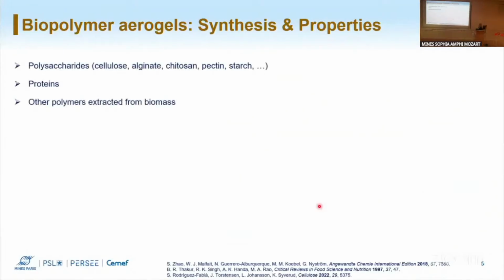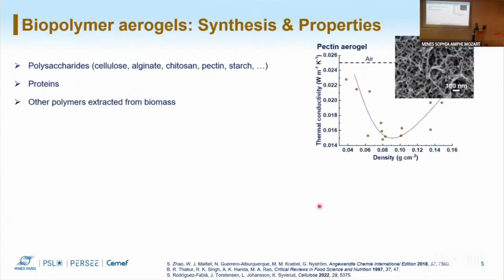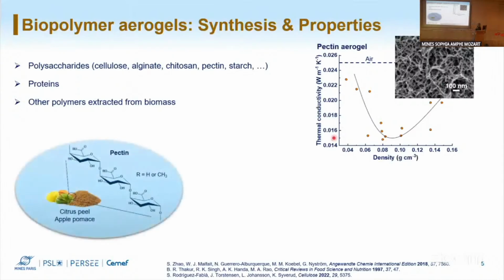Let's see what biopolymer aerogels are. Usually they're from polysaccharides, protein, or other polymers coming from biomass. And from this family of materials, we know that pectin aerogels possess one of the best properties regarding thermal insulation. We can see here that for a range of formulation, we have super insulating properties, and we can reach down to 15 milliwatt per meter Kelvin, so much below air. Pectin is usually extracted from citrus peel and apple pomace that comes from waste from the industry.